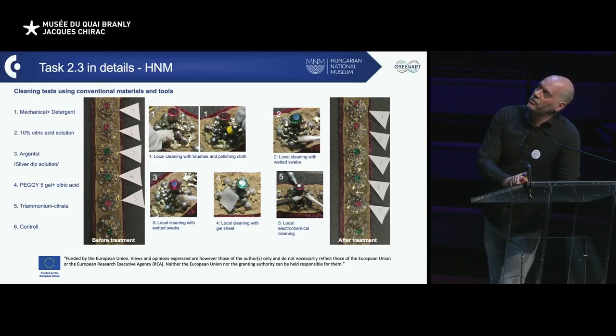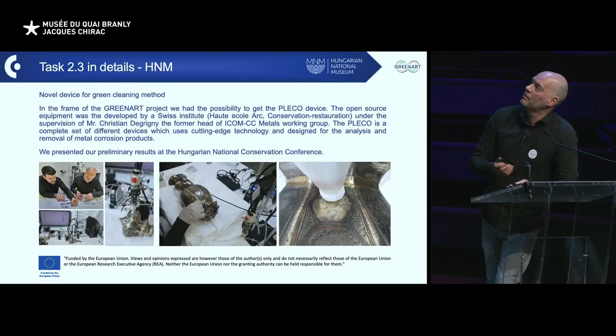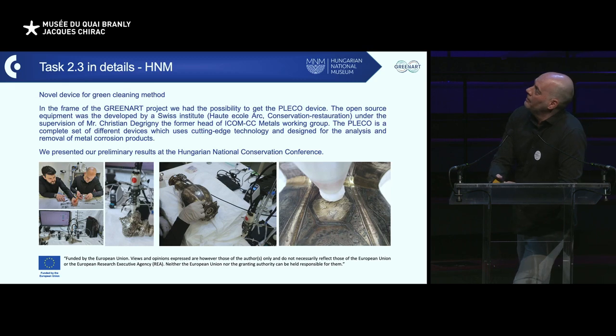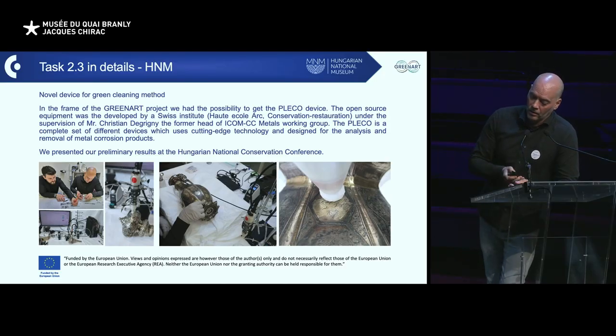Let's go on to working package 2, which is about the cleaning. So we are involved in task 2.3, and as a preliminary preparation for the trials, we did some tests with the traditional materials we use in everyday practice on the sword belt, for example, and these include mechanical cleaning, cleaning with detergents, using mild acids, some gels, some silver dip, and triammonium citrate, and also local electrochemical cleaning. We also tried to use our new novel device. It's also a kind of green cleaning method, which is called the Pleco. It's developed by a Swiss institute, and it's designed for the analysis and the removal of corrosion products. So we tried this device also. It's a kind of preparation for the comparison of the effectiveness of the green solutions.